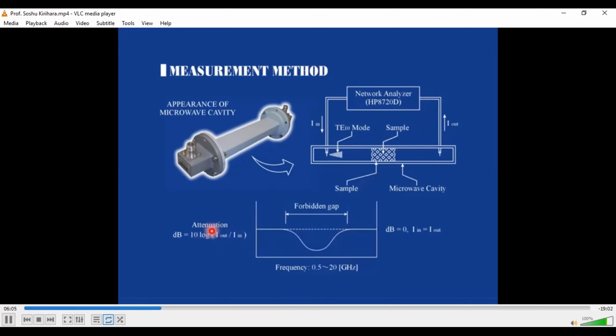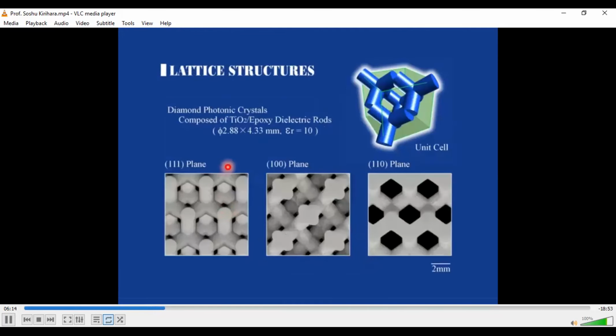The U-shape profile will be obtained. This figure shows a fabricated titanium dioxide particle dispersed epoxy diamond photonic crystal. You can see the 111, 100, and 110 crystal planes obtained according to their computer graphic data. The microwave transmits in the 111, 100, and 110 directions.